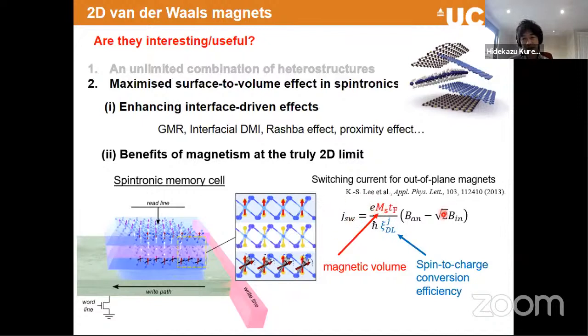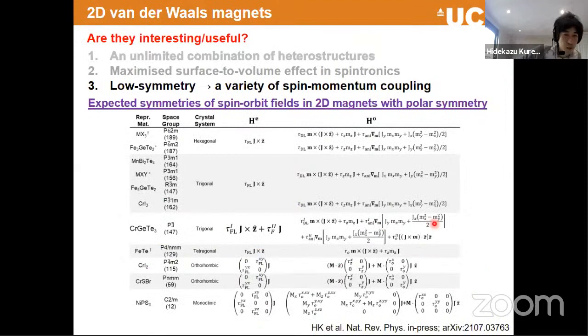So by looking at this equation, that really helps us to reduce this switching current density. On top of that, on the denominator side, this is the efficiency of how much spin we can generate by current. So this is the important parameter, pretty much like the effective spin Hall angle. And the question is whether the spin Hall angle is strong in a 2D van der Waals system. We cannot answer yes or no at this stage, but what we can tell for sure is that because of the low symmetry of the van der Waals system, these are pretty much not cubic anymore. Then we can produce lots of different spin-orbit torque components allowed by the symmetry of the system.